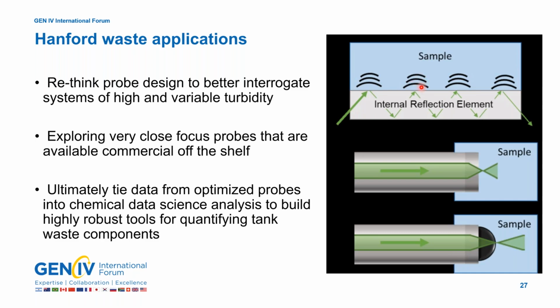In that evanescent wave, there's some attenuation. So we do measure some attenuation from the signal, and that goes off to our detector. We can then measure the Raman spectrum based on the sample that was in solution adjacent to this reflection element. We also have several probes that we're designing.